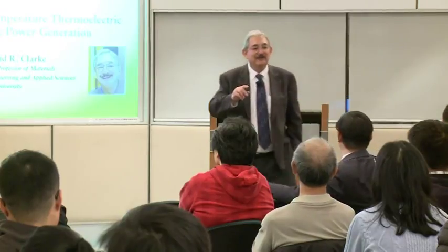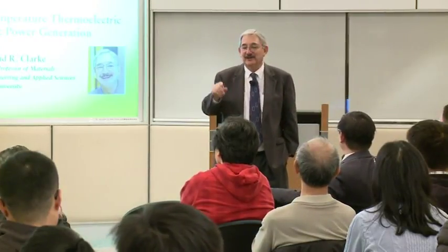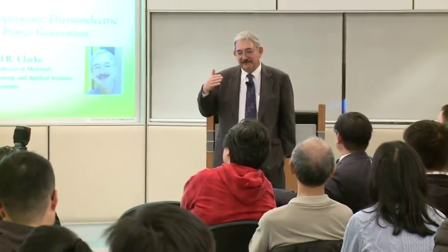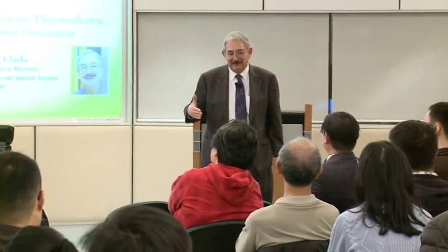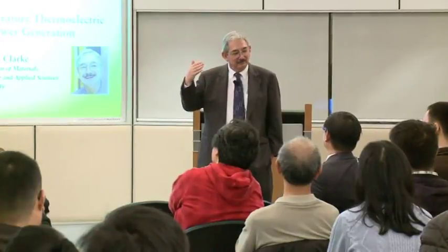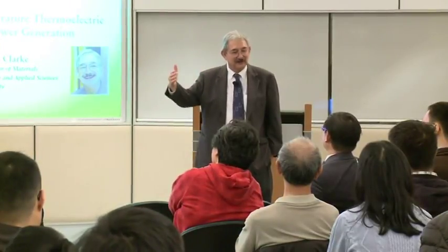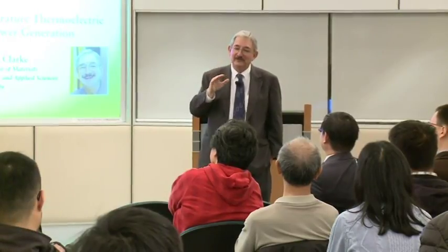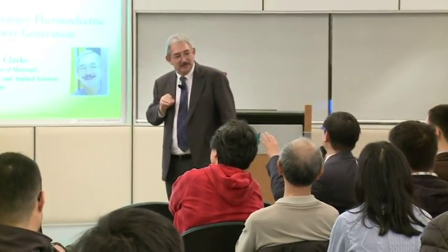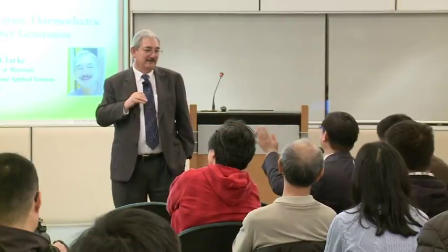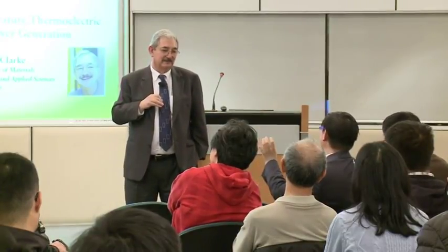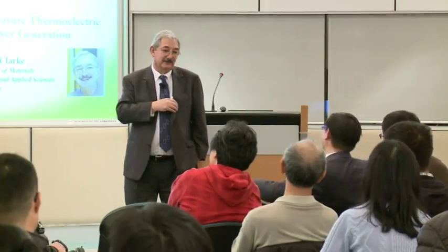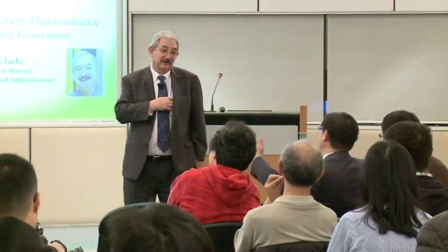So let me answer those two questions in turn. Twins will certainly affect phonon transport, but they're not very effective because you'd ideally like to have a mismatch in, say, the atomic mass or the atomic arrangement. So twins, I don't think... I talk about the stability compared to the nanograin boundary. Nanotwin boundary is more stable for the same composition.